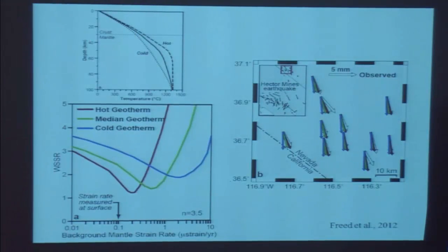One way is to make diffusion much, much more difficult. And one way of making diffusion much more difficult, which we alluded to earlier, is by going to higher and higher pressure. That's the origin of this term that you've probably heard of, the activation volume of creep. You go to higher pressures, it makes the formation of those vacancies harder and harder. You get fewer and fewer of them. Diffusion slows down, and it's possible that you move into a mechanism where the glide process becomes rate limiting. And that's some of the work that Patrick has done.